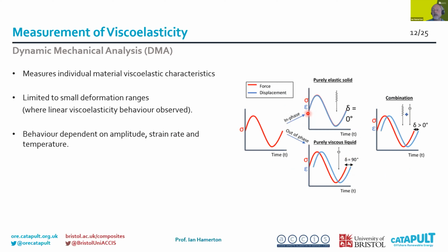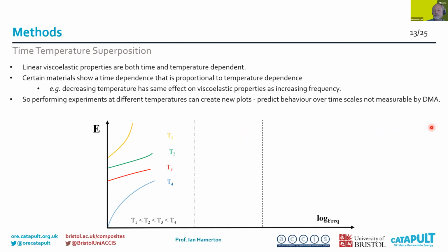In the case of a purely elastic solid, this is in phase. We get a nice tie between the applied force and the displacement. With a purely viscous liquid, we get an out of phase, a 90-degree out of phase response. Because we're talking about a viscoelastic material, it sits somewhere between the two. So we get something where we can measure the damping, this delay that is introduced. So over time, of course, the DMA is relatively limited in what we can do to test this.